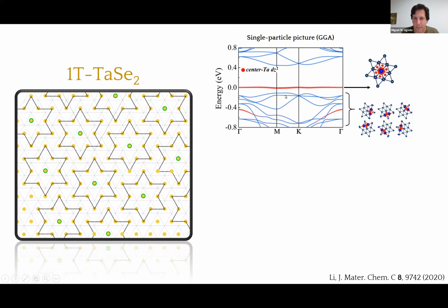12 of them are filled here, okay? And now they are spatially located in the surroundings of the Star of David. But there is one lone electron that is supposed to be localized at the center of the Star of David, in which there's one band, basically. There's one band, which is half filled, with only one electron localized at the center of the Star of David. Okay, so that is the origin of the isolated magnetic moments, right?